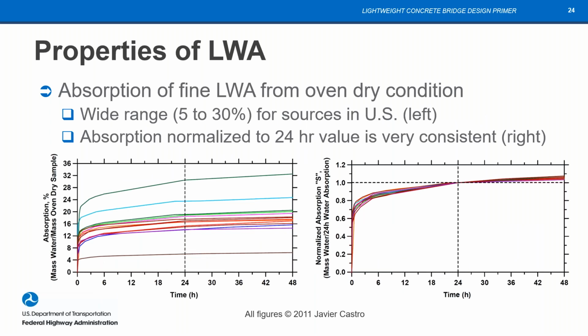Absorption of lightweight fines are shown here in two figures. On the right figure, it shows the mechanics of the absorption are essentially the same. Let's go back to the left figure. It shows the range in absorptions. You see that the bottom line after 48 hours, 2 days being soaked, it's somewhere in the neighborhood of 6%, 7% absorption, while the top one here is up over 32% absorption. So there's a fair range.